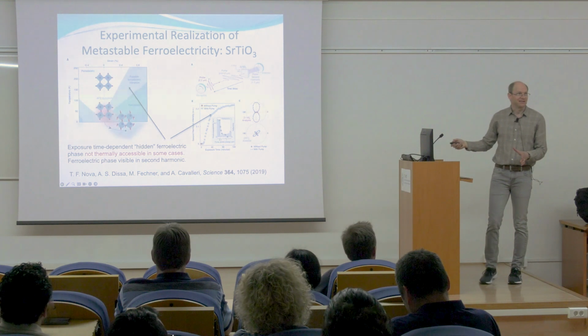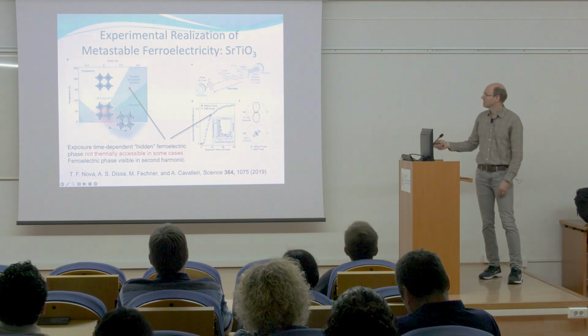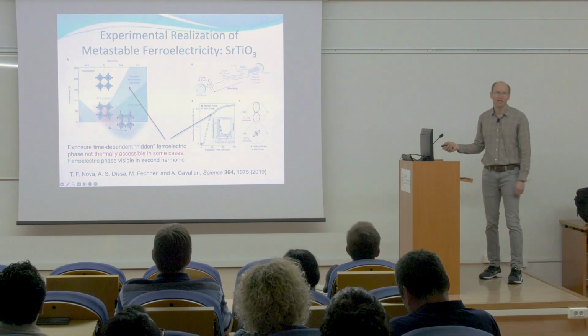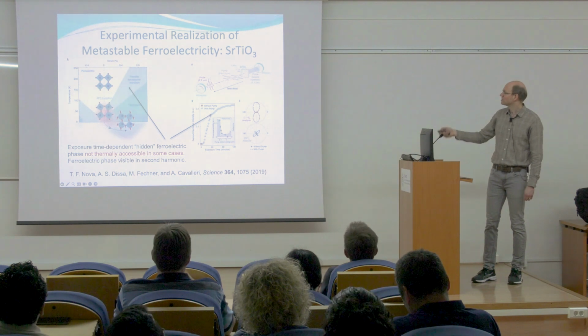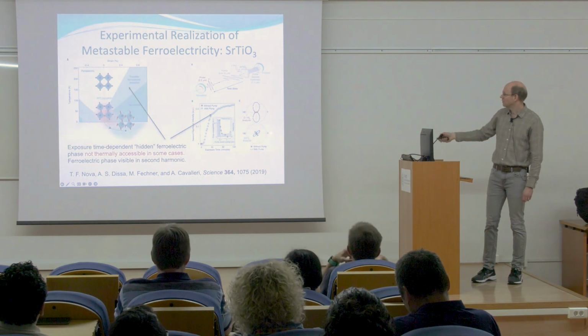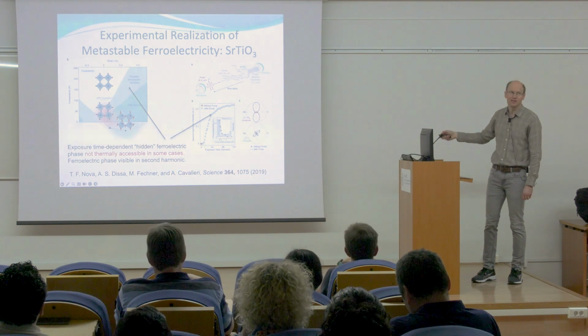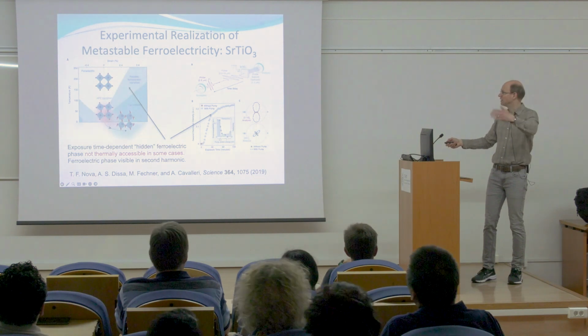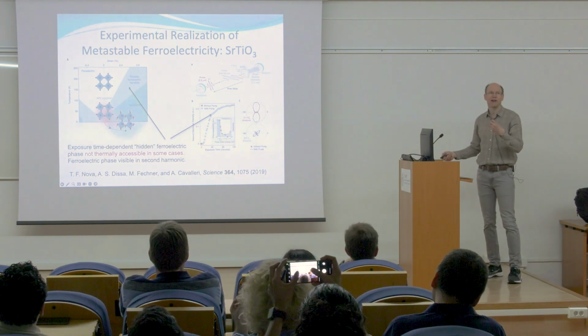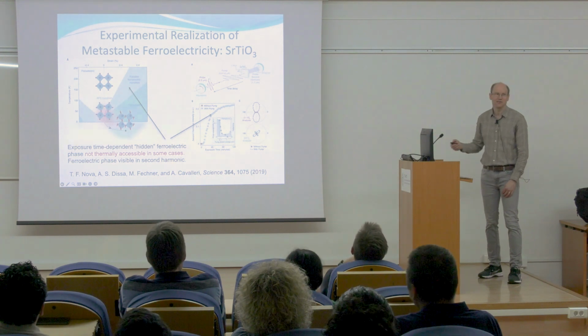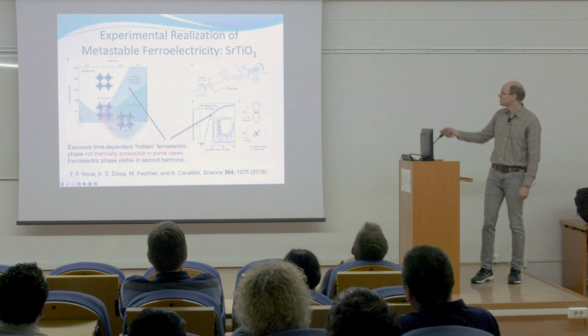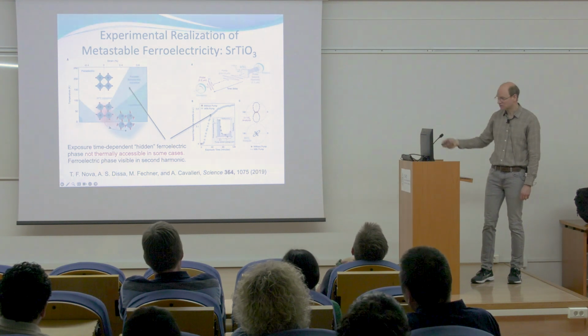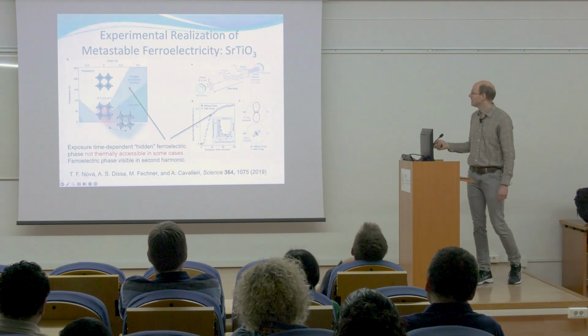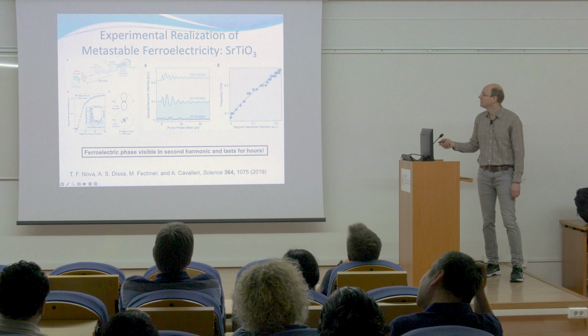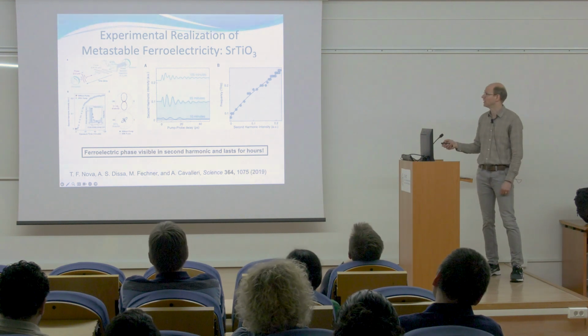However, if you do not strain the system and you pump it with light long enough, and in this case long enough is on the order of 1 to 2 hours, then you can induce this ferroelectric state, which can be observed by an experimental technique called second harmonic generation. So you send in light, and you look at the reflected light or transmitted light, which is at twice the frequency that you sent in. So that's the second harmonic. And this technique is very sensitive to inversion symmetry breaking in the system. So the ferroelectric state breaks the inversion symmetry in the crystal, and then this second harmonic signal picks up the details of that inversion symmetry breaking. So it's a way that you can probe this ferroelectric order.